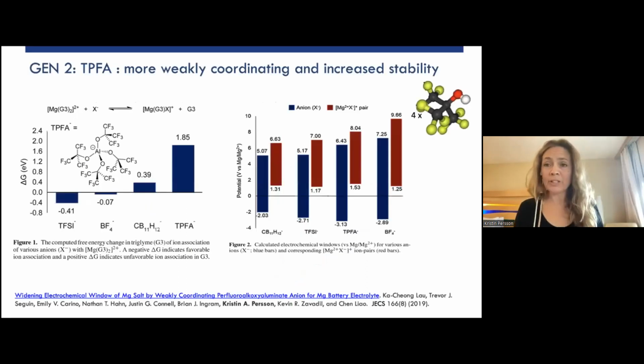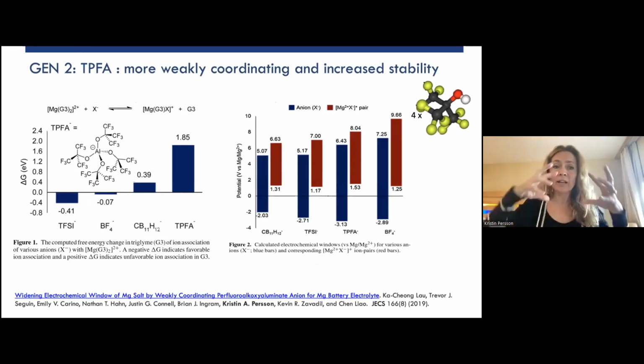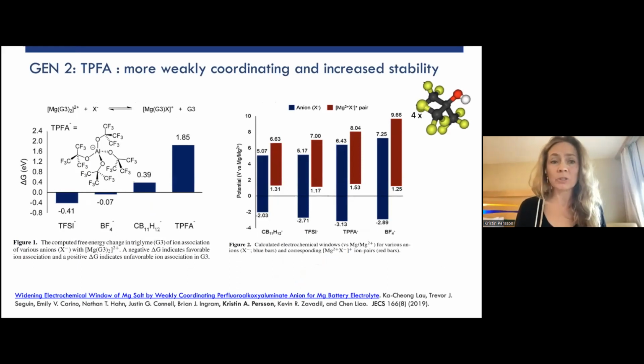In our group, together with Kevin Zavadil again and Nathan Hahn and a bunch of people from the Joint Center for Energy Storage Research, we added yet another CF3 group to this, and at Argonne they were able to synthesize the TPFA anion, which has this aluminum center and these large bulky ligands that really don't like to hang out with the magnesium metal in solution.